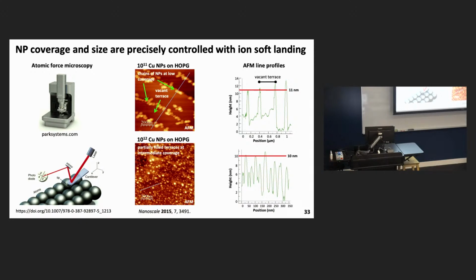So if you run the AFM tip along here, you can see the size of these is about the same, 11 nanometers. If you kick the coverage up by an order of magnitude, you see a much denser coverage, obviously, where those terraces are filled in, but the size focusing is more or less retained.